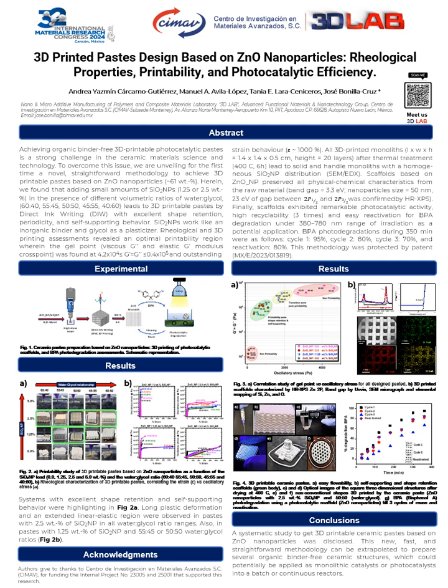In subsection B, we can observe XPS, UV-Vis, and scanning electron microscopy, where it is proven that the monoliths have the same physicochemical properties. That is, there is no variation with zinc oxide powder, since they have the same band gap and the 2p peaks are shown, just as there is homogeneity in its structure. In Figure 4, we can see that different morphologies can be made with the printable pastes. They also do not present fragility when used. The layers of the monolith have self-support.